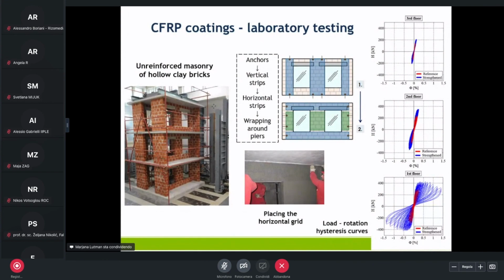And here is the slide showing extensive experimental research that has been recently carried out in the laboratory of ZAG, addressing the effectiveness of carbon fiber reinforced polymer if applied to hollow brick masonry. The damage of this full-scale model was typical for masonry structure in original and in strengthened state. Much larger drifts and damage developed in the first floor, the diagram on the right below, than in the upper two floors.